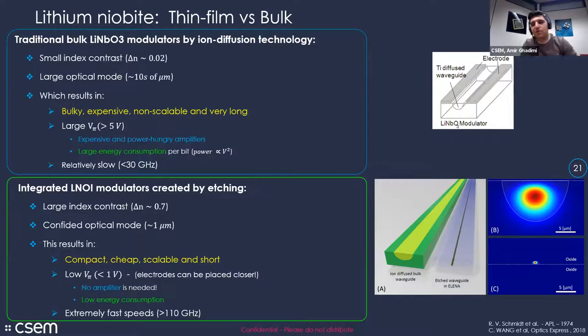Since you have such a small refractive index contrast, the mode volume becomes really large, in the order of tens of microns. So when you have such a large mode volume, a few things happen. You have to put the electrodes outside of the optical mode, so your electrodes are further apart. You have to apply a higher electric field. Your speed goes down, your power consumption goes up. And your bending radius is in the order of millimeters, so you cannot really pack a lot of things.